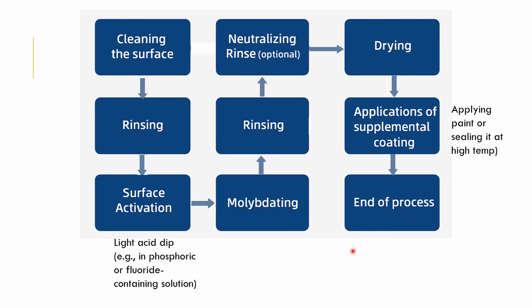To summarize the whole process of molybdate coating, first we have to clean the surface, then rinse it. Then give the surface activation, that is dip it in light acid dip. What is that light acid used? Phosphoric acid or fluoride containing solution. After that you give the molybdate coating. Once the molybdate coating is given, then undergo rinsing.